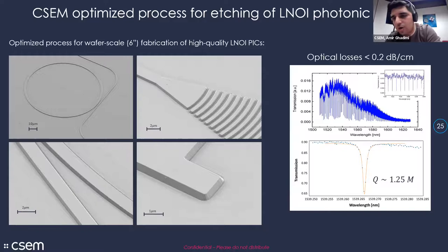This is not really the highest or a record. The record is roughly 7 times this value. We have record quality factors of 7 or 8 million. I have to check my notes again, but in that ballpark. But we would like to report mean losses, because when you're trying to establish a foundry, you're not basing your PDK on records, you have to rely on the mean, because you have to guarantee a certain performance.